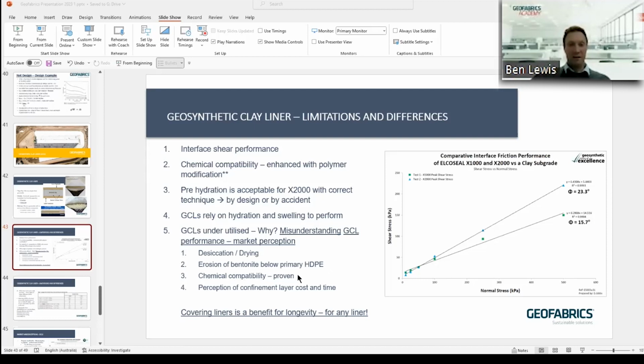Chemical compatibility, I think there's a lot of concern around how GCLs and bentonites perform and swell or don't swell with different chemistries. But in reality, what you see with GCLs in maybe a higher pH solution is it'll start to limit the swell. And that can be bad, but at the end of the day, instead of being 1 times 10 to the negative 11 meters per second, it drops to 1 times 10 to the negative 9. So still in the realm of a compacted clay liner. It doesn't completely destroy the performance. It just increases that hydraulic conductivity value. And again, we've got data to back that up.